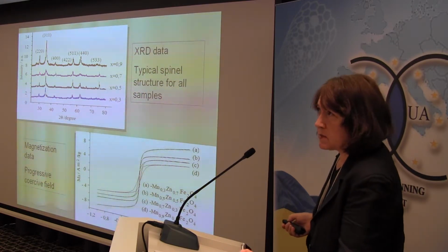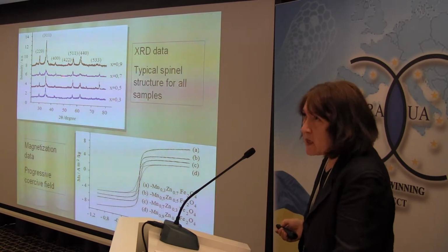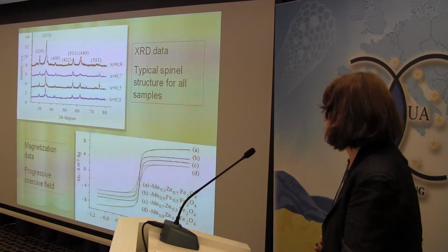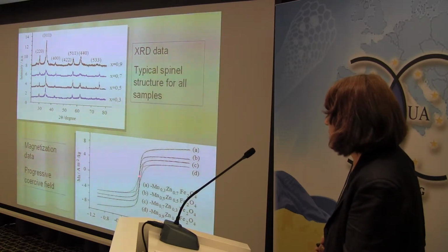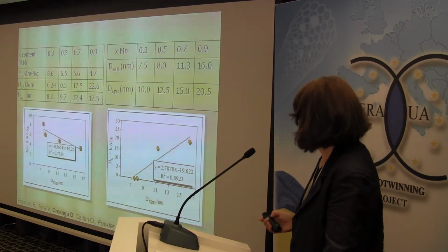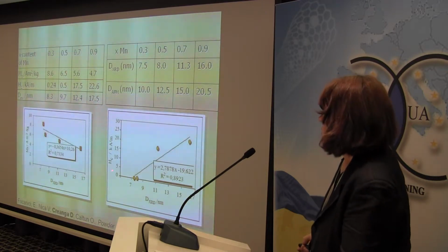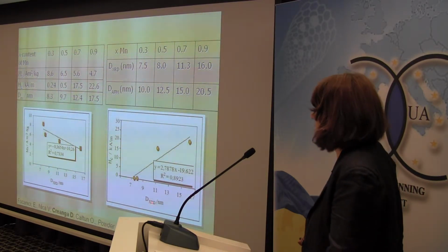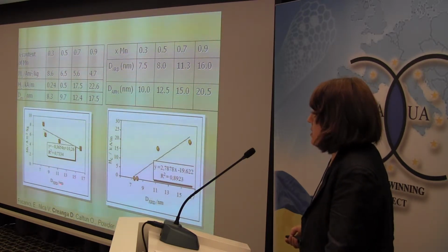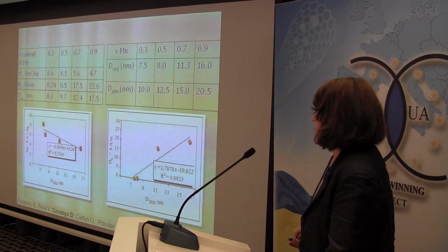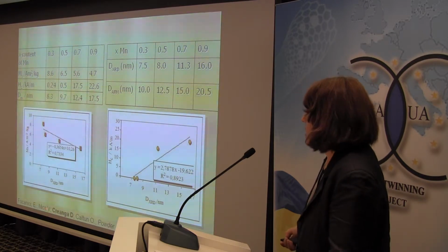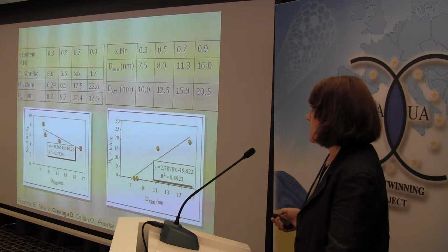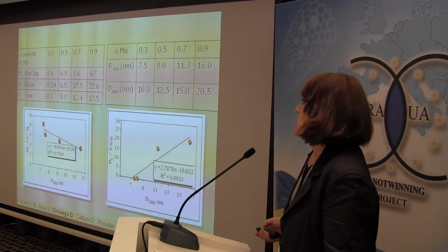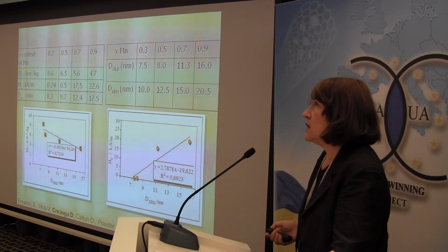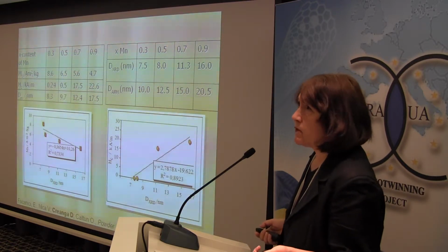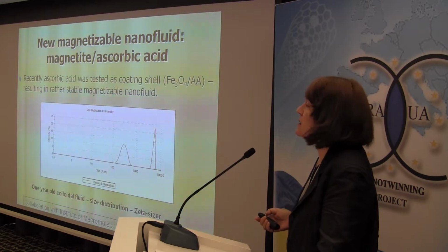All of the same spinel structure, whatever the manganese content was, except for the magnetization data, where progressive coercive field increase was evidenced with the increase of manganese content. There was some correlation between the coercive field and the crystalline size, as well as between the saturation magnetization and the crystalline size. And another group where our colleague Nika Valentin was working was able to demonstrate some interesting calorimetric properties of these fluids that recommend them as cooling fluids for industrial devices where heat in large amount is released.